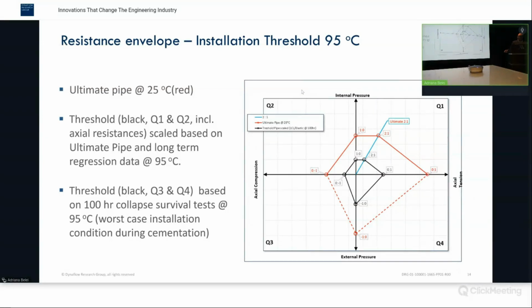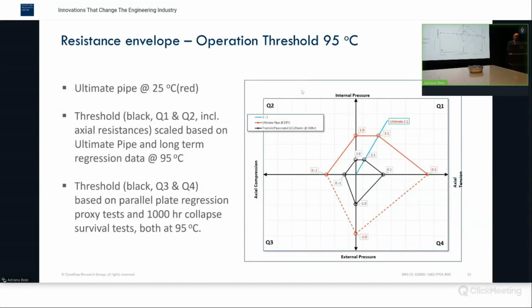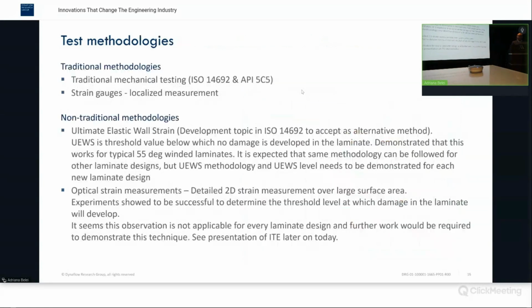So the threshold for the external pressure that's indicated here is based on a 100 hours collapse survival test. And the basis for that is that we use parallel plate testing to measure a regression gradient for this material. And you demonstrate that you can determine the threshold value by a 100-hour survival test at 95 C. For the operation threshold, it's actually the same as for the installation envelope. The difference is the survival test that is carried out at 1000 hours.